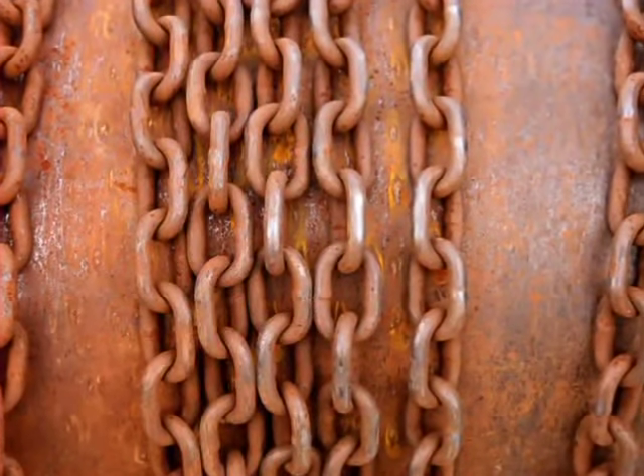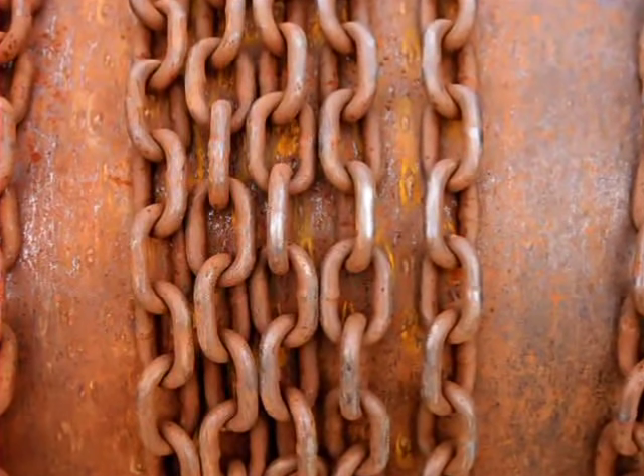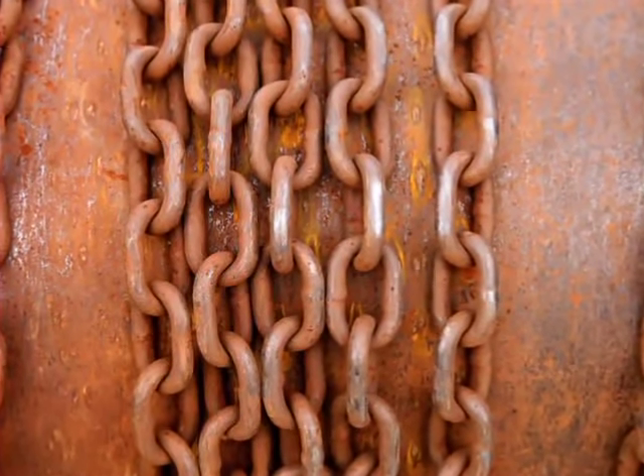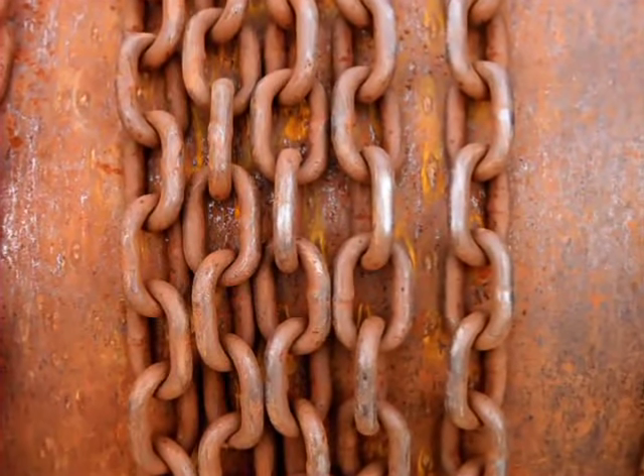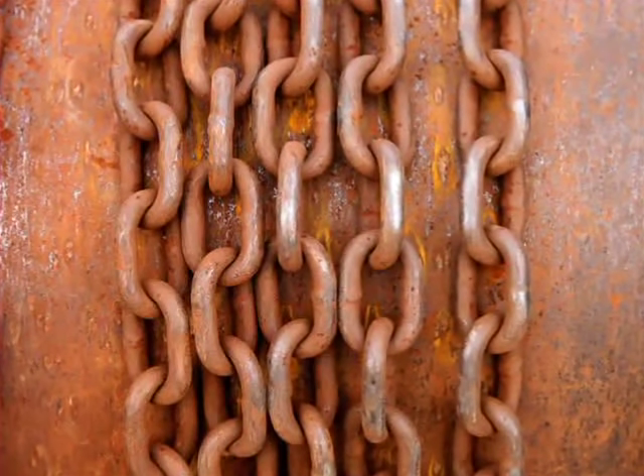First, it's susceptible to corrosion, the long-term deterioration caused by the chemical reaction between iron and oxygen. You probably know this phenomenon as rusting. It also has very poor fire resistance. By the time steel reaches 900 degrees Fahrenheit, it will have lost about 30% of its tensile strength. By 1400 degrees, it will have lost nearly 90% of its strength.